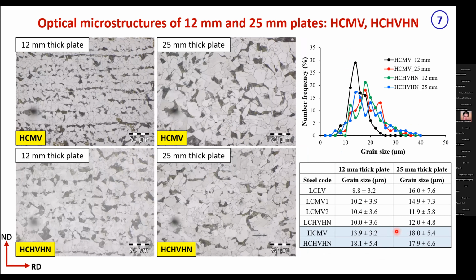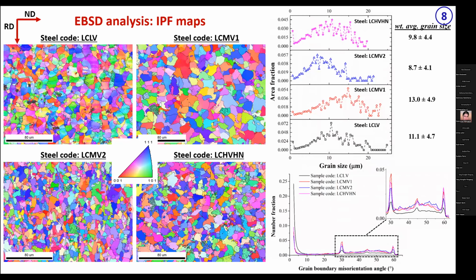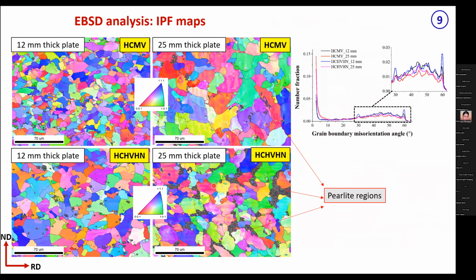So grain size problem, we would have loved to have a smaller grain size, possibly. As I talked to my collaborators, Dr. Kumar and Mr. Aniket at SAIL, they said that the furnace temperature was a bit high, and it was behaving a bit erratic because it was newly installed. So that and the rolling schedule also, there may be some issues for which grain size is a little higher. So you can see the last time, these are the EBSD maps I presented. And this time, these are the EBSD maps. So you can see the grains are slightly higher, but it's a nice ferrite pearlite microstructure altogether.